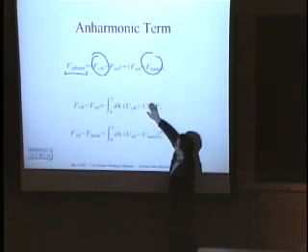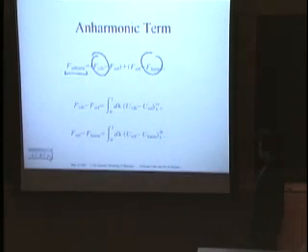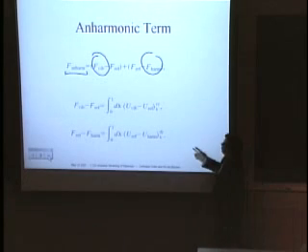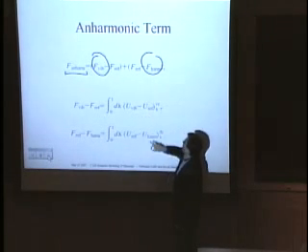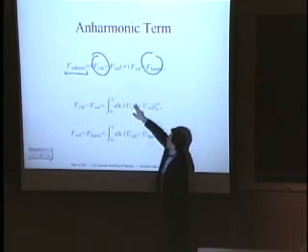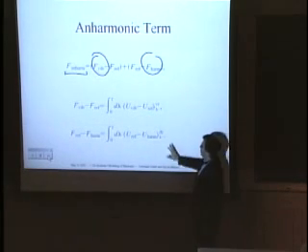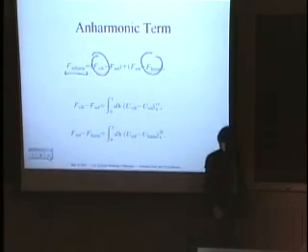While this that is very expensive, because you need to calculate the internal energy with the quantum mechanical model, you are trying to sample the difference between two quantities that are as similar as possible, and, in the ideal case in which your classical potential is able actually to reproduce your quantum potential, this goes towards 0. So it's something that is very simple to integrate.